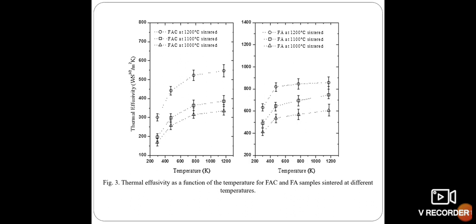Then this one represents the thermal effusivity as a function of the temperature for FAC and FA samples sintered at different temperature levels. From this, it can be observed that it depends on the specimen's densification as well. Thermal effusivity values for FAC and FA are temperature dependent, and these values change in the whole temperature range from 170 to 550 and from 400 to 900 for FAC and FA samples respectively. Therefore, FA samples present higher effusivity values than the FAC samples.